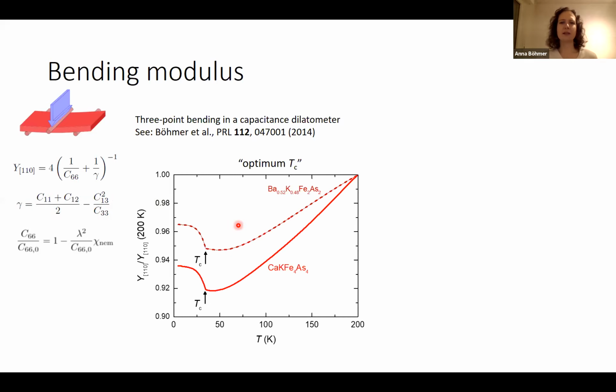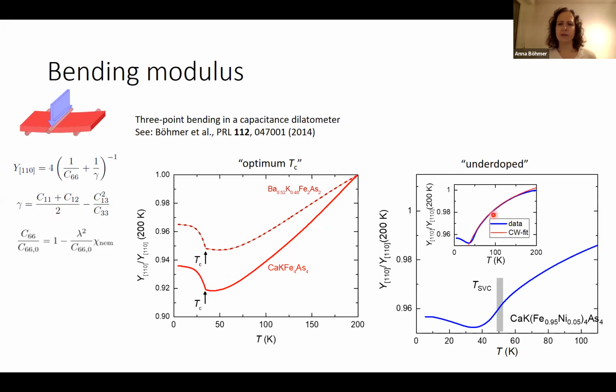So let's go to the results. This is the optimum TC sample, the pure 1144. You see a softening of the Young's modulus, which comes from a softening of the shear modulus, and a significant hardening below TC. This is very similar to the 122 that corresponds at similar doping level. On the other hand, for the nickel-doped one, or what would be an underdoped one with a magnetic transition, I do know what the temperature dependence of the Young's modulus will be if there's a Curie-Weiss-like temperature dependence of the nematic susceptibility, and that's what this red curve shows you, and it works very well. So here again, we have evidence for a Curie-Weiss-like divergence of the nematic susceptibility. There is a very curious, very subtle anomaly at the spin vortex crystal magnetic phase transition here.